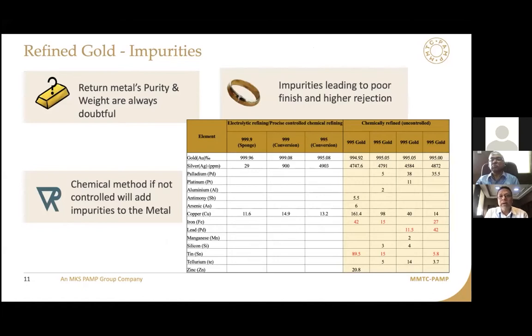If you see electro refining gold, you get 999.9 with limited silver and copper in it. Then when we convert it into 999 for making 100-gram bars or 1 kg bars, or 995 in most cases, everybody is adding silver, and sometimes some people add copper, but very few add copper. In this case we almost add 5 grams of silver per 1 kg of gold, and the rest is copper.